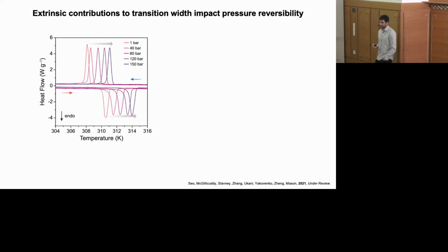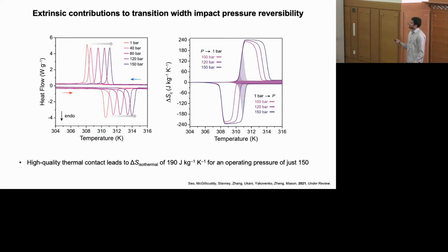And this is a point that had been overlooked actually in most of the literature in this area. And so when we look at our single crystal samples that have really good thermal contact, we're now able to induce reversible isothermal entropy changes about 3 times higher in magnitude at an equivalent pressure. But still, the temperature range over which we can induce these reversible entropy changes is quite modest compared to what you would actually need to be able to have a useful cooling device.